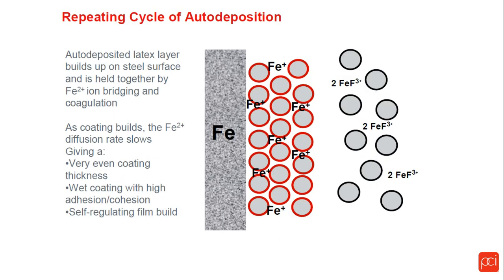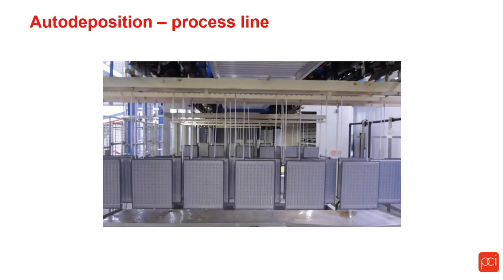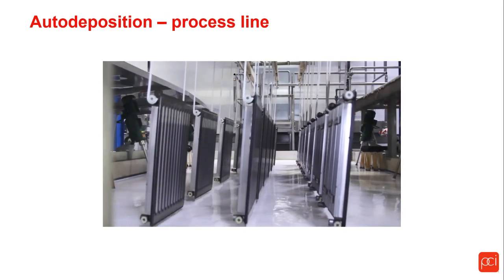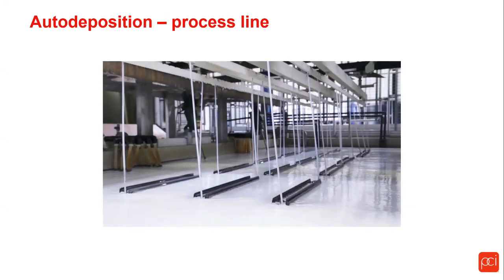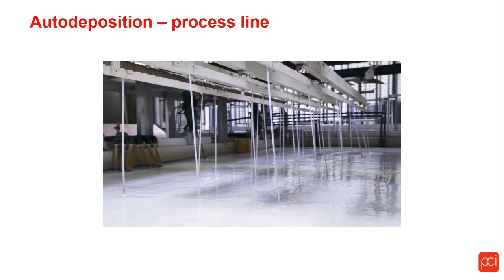Auto-deposition is a self-limiting reaction. As you can see in this graphic, once it can no longer etch, it can't grow the coating anymore. So it is a self-regulating product. This is an example of an auto-deposition bath, and auto-deposition baths are immersion tanks. So where it wets, it coats, and it can do the inside of a part just as well as the outside.